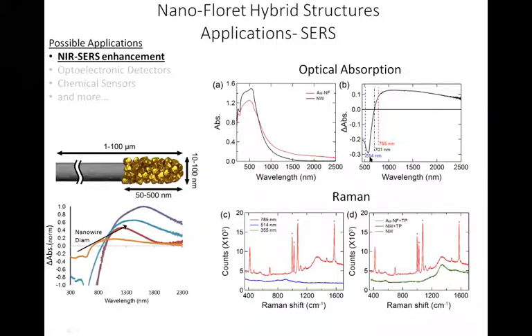So this is how the optical absorption looks of a film of these nanoflorets. So we measured the nanowire, and then immediately after it is transformed to a nanofloret. And by a difference, you can see this very broad absorbance that goes all the way up to higher than 3 micron wavelength. And the reason it is cut at 2,500 nanometers is simply the limitation of the detector we had. So we utilize this broadband plasmonic absorption and tunable features to demonstrate near IR surface enhancement, as you can see here, for example.